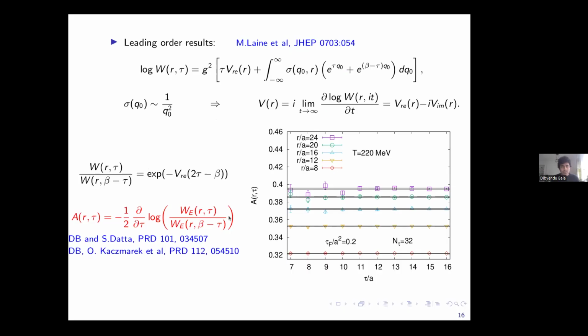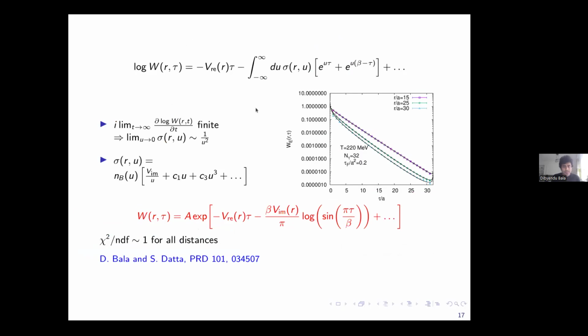Okay, and this is the analytic understanding that we have performed. And using this analytic behavior, we have constructed this Wilson loop. Again, this is the non-perturbative behavior. Now we confirm it. And this Wilson loop is now again given by this exponential of V(r)τ with some extra term. That is what Padmanabh was asking me. This is the extra term that has to be put in on top of the pure exponential decay. And that is the part that does not give you the plateau.